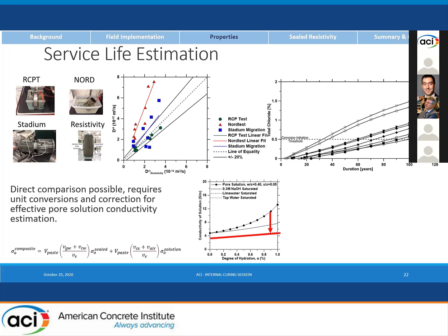We can crank through with one of those diffusion coefficients in perhaps a nice model for service life. We can set some threshold for the initiation of chloride. We can say this is where our current class of materials are. We can take a look. I think I skipped past it. So the non-internally cured mixtures that were our references, we had a couple that were lower performing and a couple that were high performing. All of the internally cured mixtures, anywhere between 60 and 90 years is what we're estimating the initiation for corrosion is going to be.